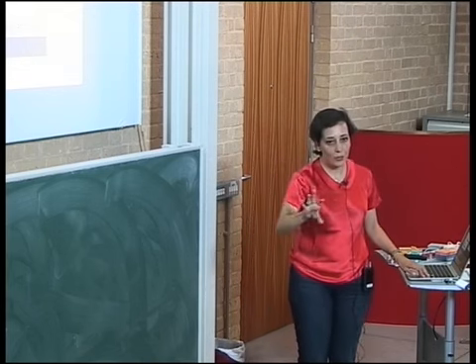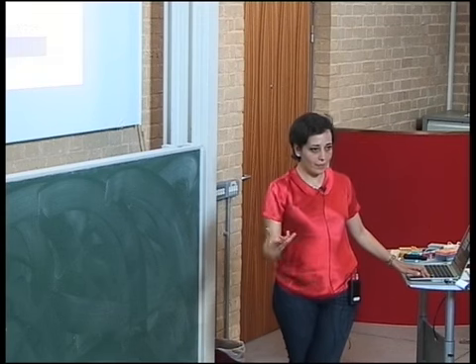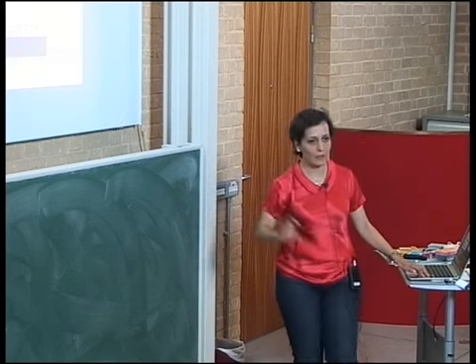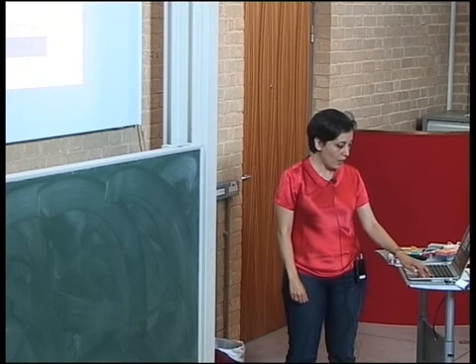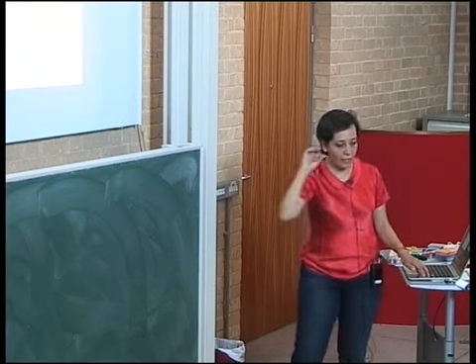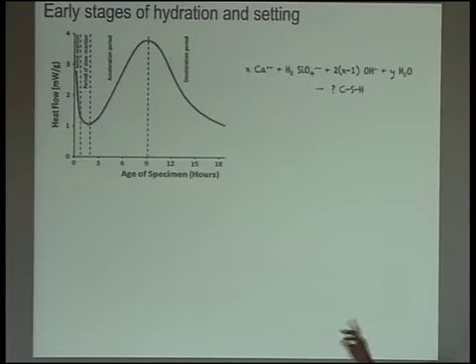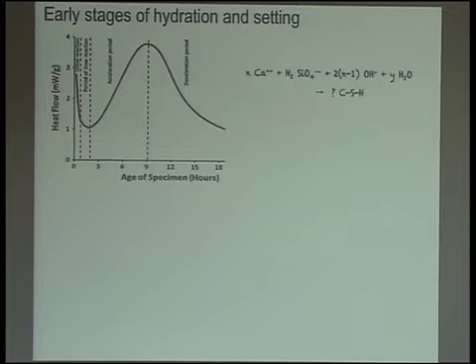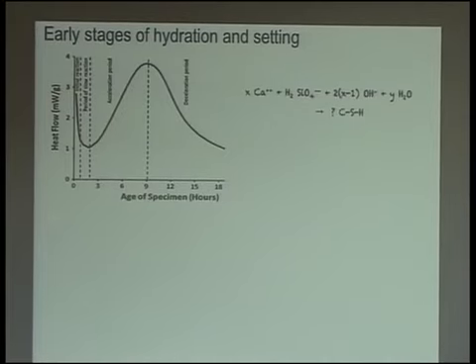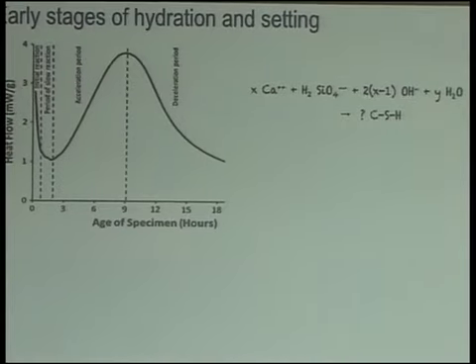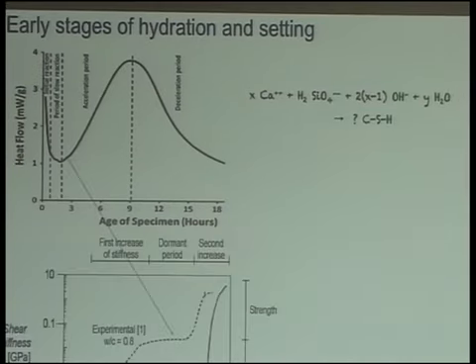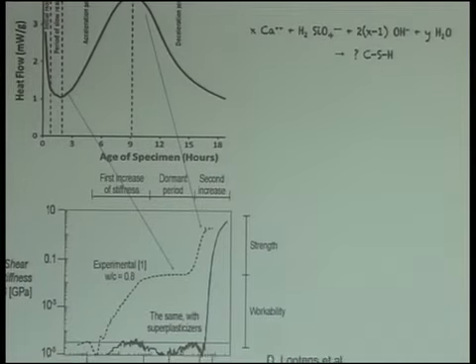I just want to tell you what is the particular perspective that we use in this type of very complex problem. It's a very complicated problem. One interesting thing is that you can follow the hydration reaction, which is exothermic, so you can monitor the heat flow released during the reaction. And so you have this hallmark that is given by the acceleration and deceleration period in the kinetics of the hydration. What is interesting is that these features are coupled to changes of the morphology of the gel.